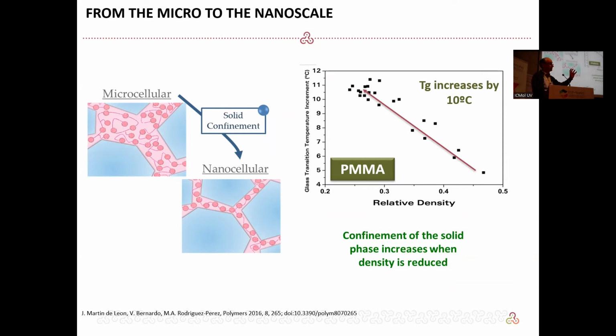So we have the polymer. It has a glass transition temperature characteristic of that polymer. If we make a nanocellular polymer with this polymer, the glass transition temperature is much higher. So the energy needed to activate molecular movements has increased by 10 degrees C, which is very high, in fact. So we have a different organization, and this is probably the reason for this much higher mechanical performance.